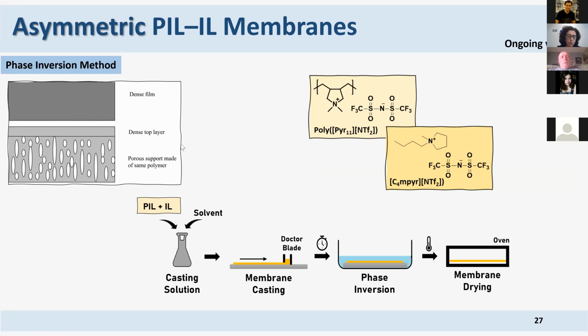And what we do first is exactly the same. So we have a casting solution. We use a doctor blade knife and we cast our membrane. And then we just wait for a certain period of time for it to evaporate a little bit of solvent on top and to start to solidify or gellify. And then we put our membrane inside a phase inversion bath, a coagulation bath with a non-solvent, for a very long period of time, typically overnight. Then we take the membrane out and we dry the membrane.